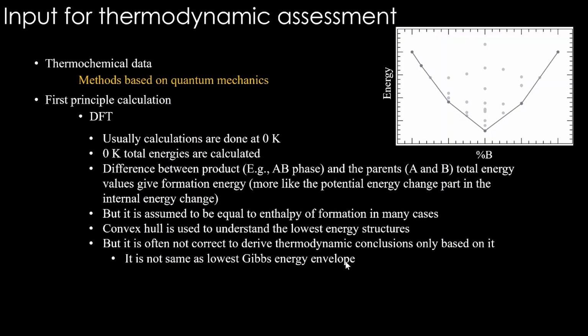People figure out crystal structures of different compositions of many functional materials based on DFT, and only based on this they talk about whether the particular structure will be stable or not, whether certain dopant will be accommodated into a structure or not, things like that. But you can sense that the entropy part is missed. If it is missed, it's a bigger problem. If the configurational entropy is missed, it is still okay for many compounds because they may not have any chemical disorder. But when it comes to vibrational entropy, it can be quite significant. Okay, so vibrational entropy change cannot be ignored.